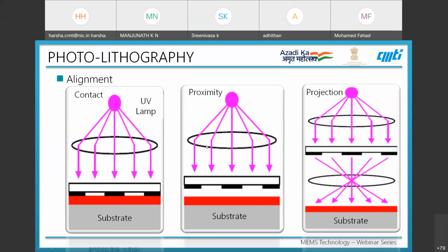In the proximity method, the difference is that there is a gap between the substrate coated with photoresist and the mask. This can be achieved by placing the mask using a spacer in between both the substrate and the mask, so there will be a gap between the mask and the substrate. This method is called proximity alignment.